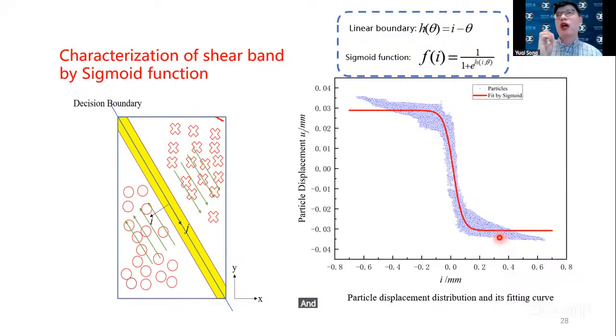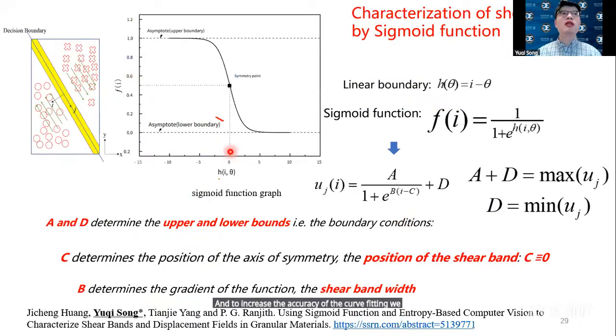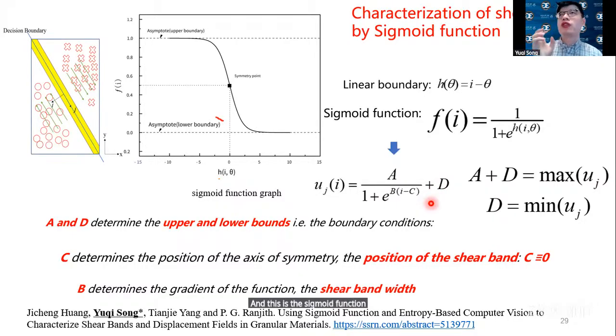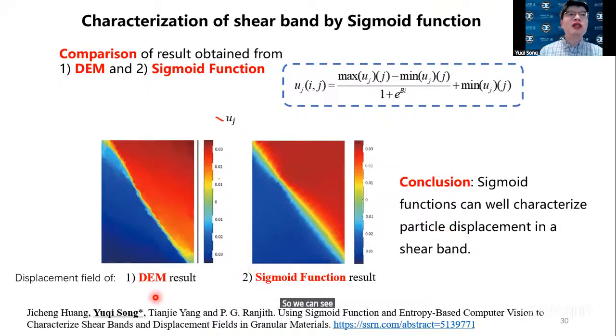To increase the accuracy of the curve fitting, we cut the shear band into 7 pieces, in this direction. We do the curve fitting for each piece separately, and finally put them together. This is the sigmoid function, and we have given some physical meaning to each parameter. It's not only a curve fitting, but it has real physical meanings. The left figure is the DEM result and the right is the sigmoid function result, and they match well.